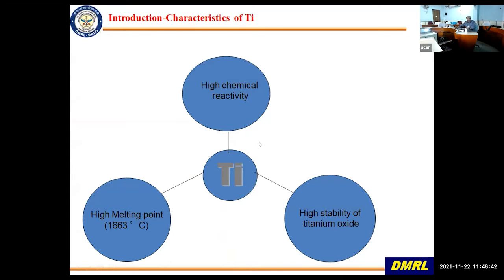Now, as far as titanium goes, it is basically extracted from its oxide, which is available a lot in the Kerala beach sands, and this titanium oxide is very stable. As a mineral, it occurs as rutile and ilmenite. I will not go into the process metallurgy because that is not the point of the talk now, but I just wanted to introduce it. Because of its high chemical reactivity and higher melting point, it took some time to isolate pure titanium, and it is still industrially extracted by the Kroll's process. That is, TiO2 is converted to TiCl4, and then it is reduced with magnesium.